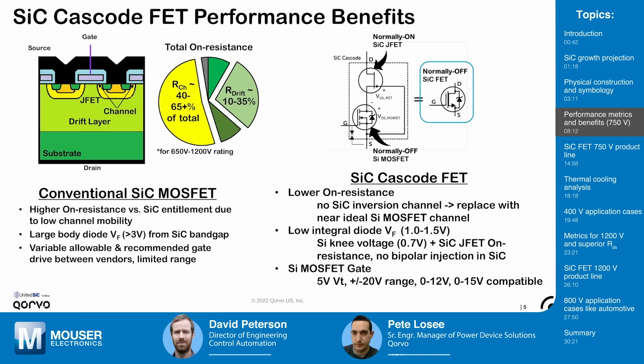So this gives the advantage of a lower RDS on per unit area for the cascode FET compared to a conventional MOSFET. The other advantage comes, as I said, from the low integral forward drop, because you're only dealing with a 0.7 volt knee voltage in the silicon MOSFET. In a wide bandgap device, turning back to the figure on the left, the PN junction of the integral diode is actually built out of the silicon carbide. So in this case, the built-in potential may be between 2.8 and 3 volts, and the forward drop of that integral diode is well over 3 volts. And this is sort of a material limited parameter stemming from the wide band gap.